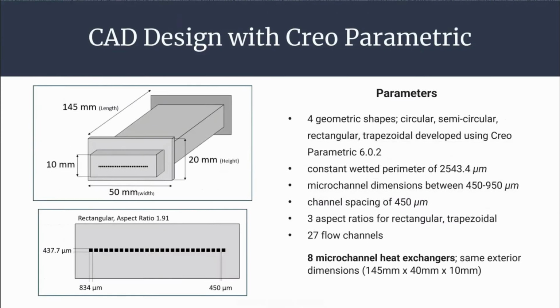So at the end of the day, what we came up with was 8 different microchannel heat exchangers utilizing 4 geometric shapes: circular, semicircular, rectangular, trapezoidal. These were all developed using the CAD modeling software Creo Parametric 6.0. We had a constant wetted perimeter for all 8 microchannels of 2,543 microns. We fell within our microchannel dimensions, classified as microchannels, and also worked within the resolution capabilities of the EOS M280 printer. And we had to maintain a regular channel spacing and our aspect ratios for the rectangular and trapezoidal shapes, as well as trying to get as many flow channels as possible across the face of the heat exchanger. We wound up with 27 flow channels each across all 8 heat exchangers.